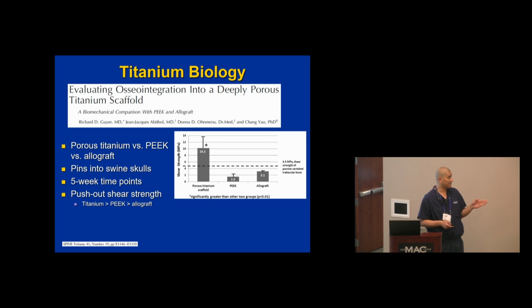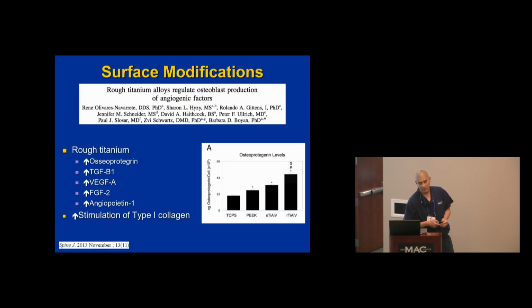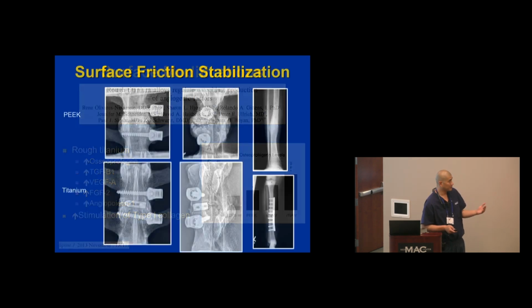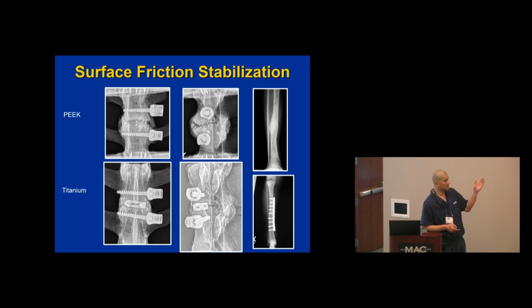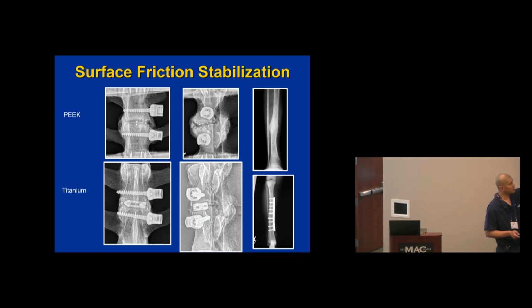They looked at the strength at 5 weeks, push-out strength, and titanium is better than PEEK, which is better than allograft. Surface modifications, now you start roughening the titanium, so you get ingrowth, ongrowth, and they found that with rough titanium, you get increased stimulation of type 1 collagen and even better fusion rates. And I think the real difference between PEEK and titanium is PEEK, because there's no initial friction fit, gives you this calloused bone formation like it is when you break a bone and you don't brace it. Whereas if you have roughened titanium and you have smoother bone growth, non-callous formation, it's like plating a bone.